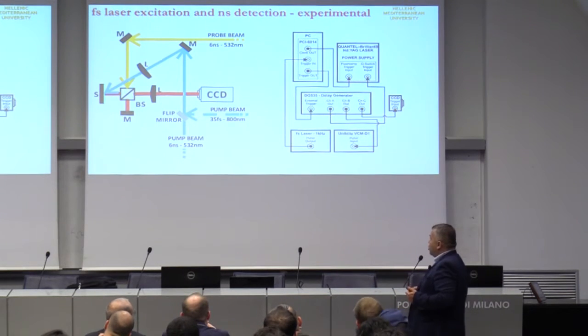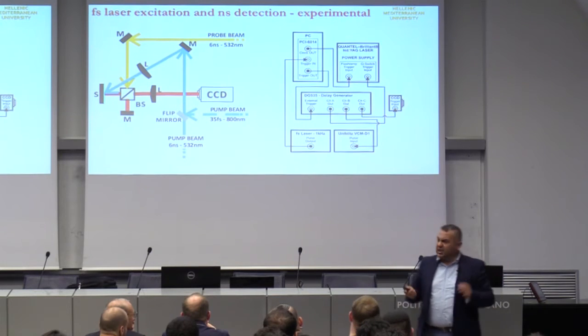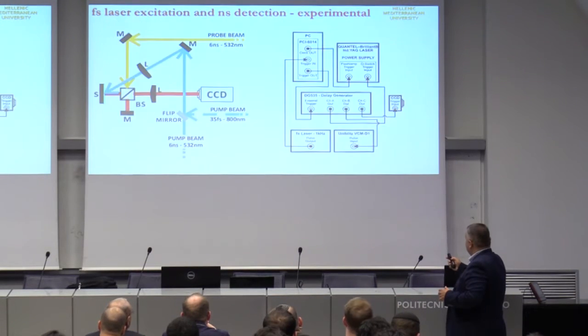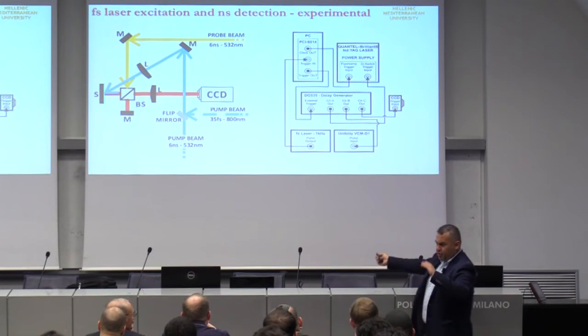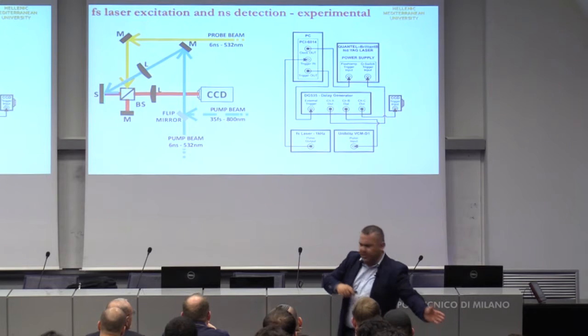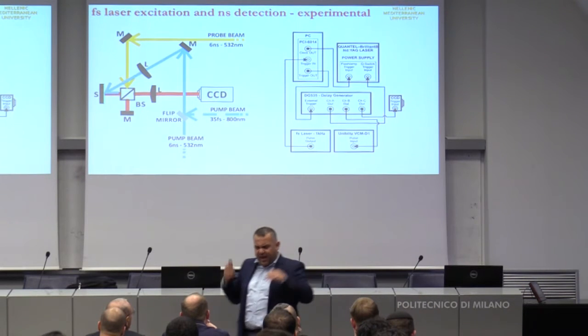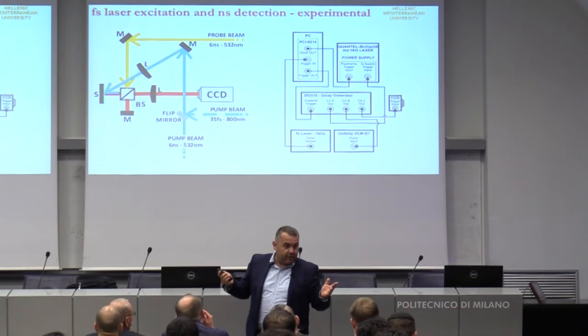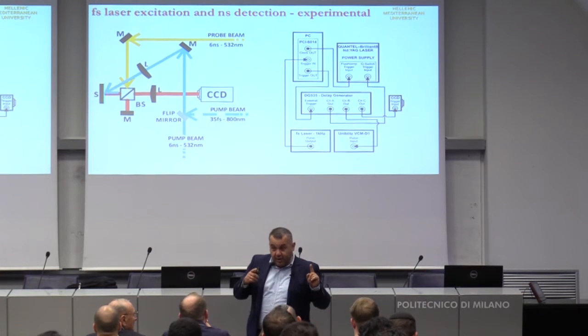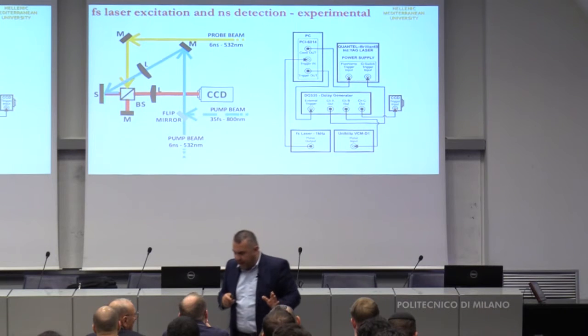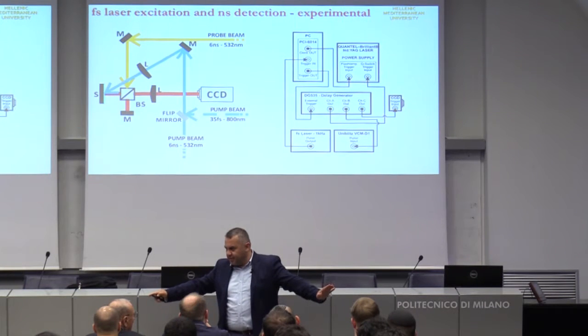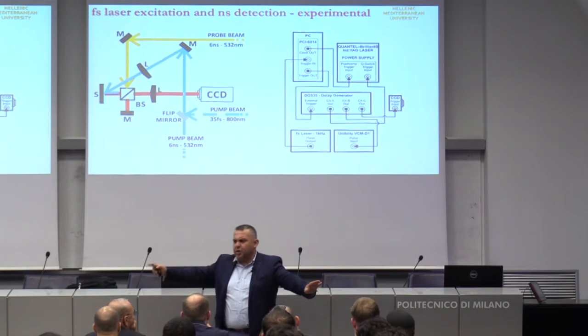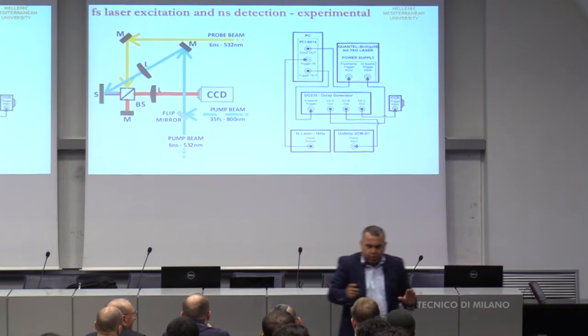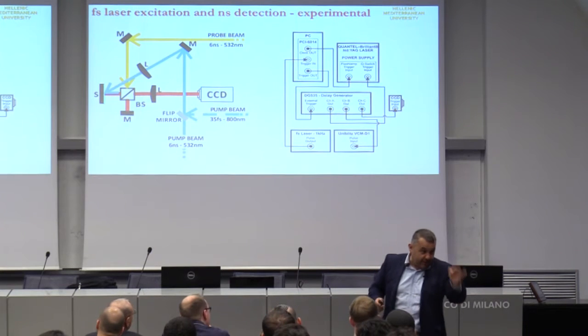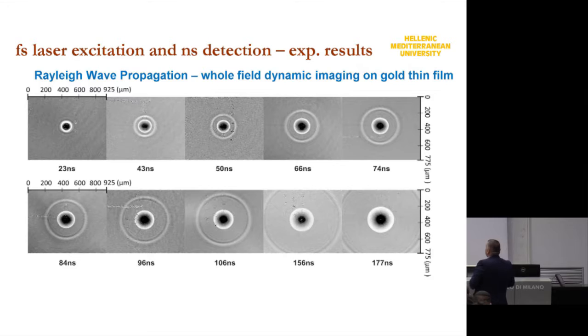So, what is also good? If you have a femtosecond and a nanosecond laser, it's very tricky to control the time between them because the one is kilohertz, the other is hertz, sometimes different pulse duration, different lasers, flash lamps, a lot of different electronics. But if you are able to do that, you can do any delay you like. Because you have a femtosecond delta pulse and a nanosecond pulse at any delay you like. You can play with your electronics and you do a cinematography, really cinematography of your Rayleigh waves. And this is the proof.